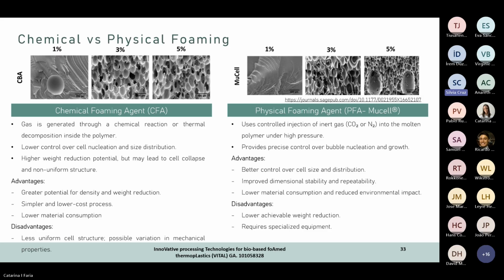The chemical variant does not require modifications to the injection unit, needing only the shut-off nozzle. The foaming mechanism is promoted by the reaction of the chemical foaming agent in the polymer melt due to the high temperature, as Johanna already has mentioned. Some chemical foaming agents are exothermic, which can promote an early foaming, reducing the residence time for the material, and consequently the cell structure is not uniform in most cases.